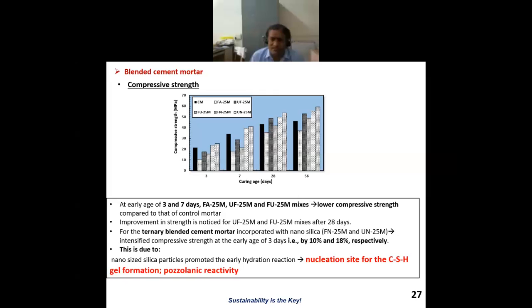So what can this be attributed to? It is due to nanosized silica particles promoting the early hydration reaction, and what is the phenomenon? Nucleation site for the CSH, calcium silicate hydrate. I showed you in one of the simulation pictures by Thomas et al. in the beginning, so maybe it helped us in a similar way. So nucleation site for the CSH gel formation and the pozzolanic reactivity. So that has helped in improving the early age strength for the ternary blended mix, which contains a very small percentage of nanosilica. A significant increase in the compressive strength at the early age is obtained, that we can see here.